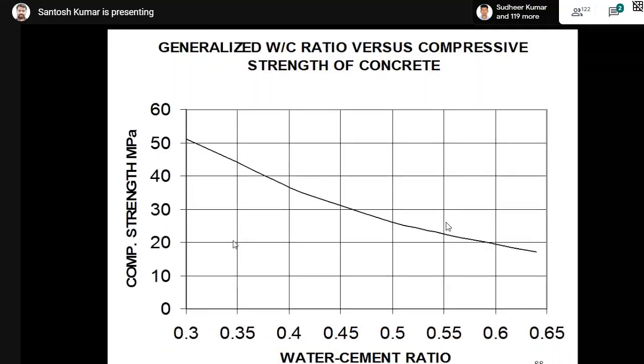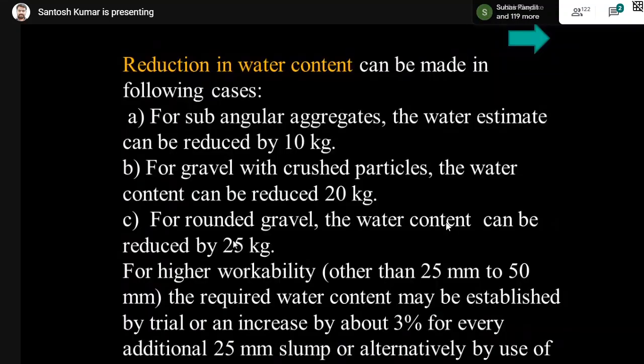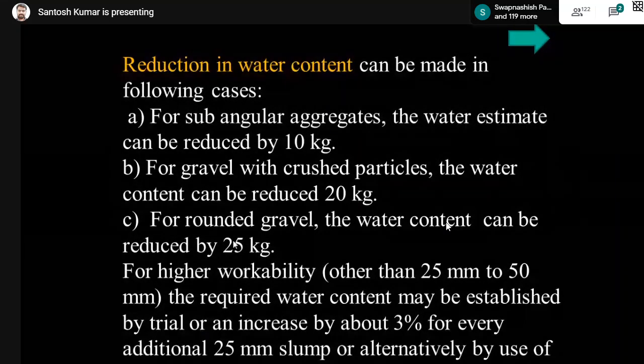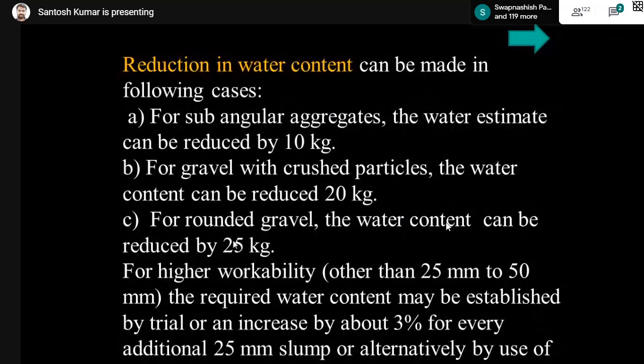Now this is a generalized water cement ratio versus strength graph. We all know as the water cement ratio reduces, the strength will increase. So reduction in water content can be made in the following cases. By using subangular aggregates, you can reduce the weight by 10 kg for the coarse aggregates. For gravel with crushed particles, you can reduce by 20 kg. Rounded gravels, you can reduce by 25 kg.